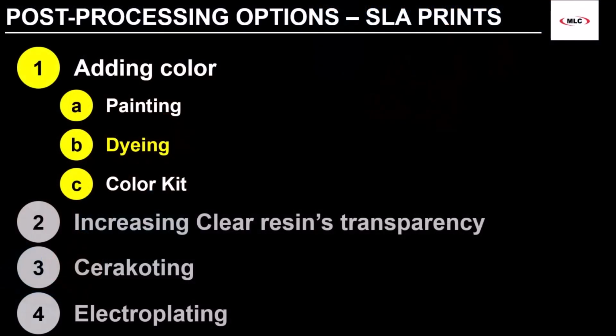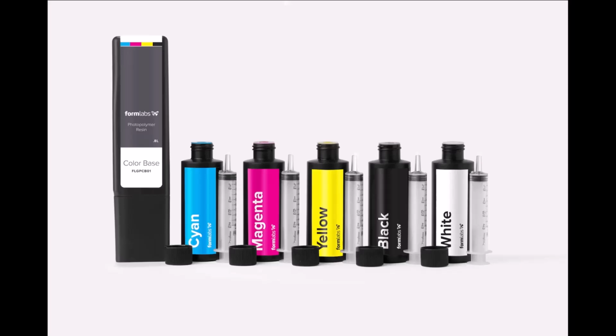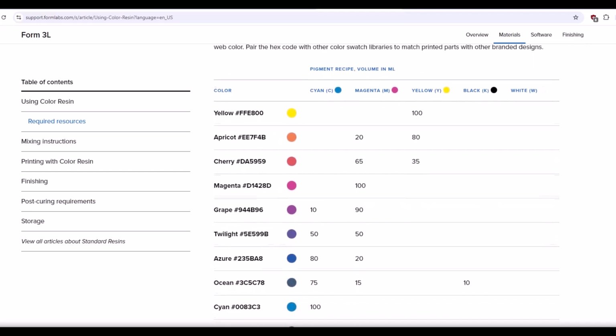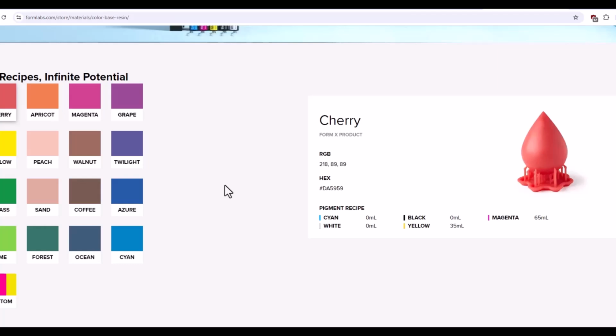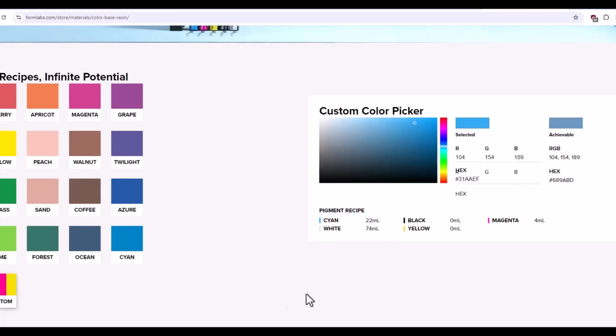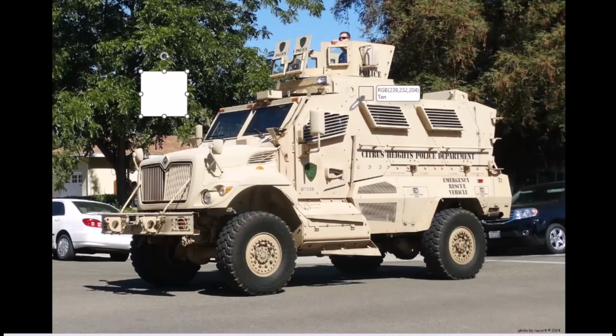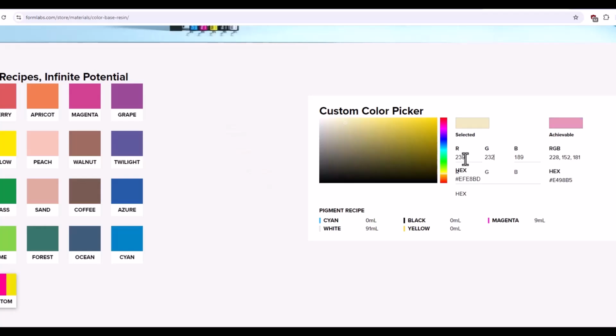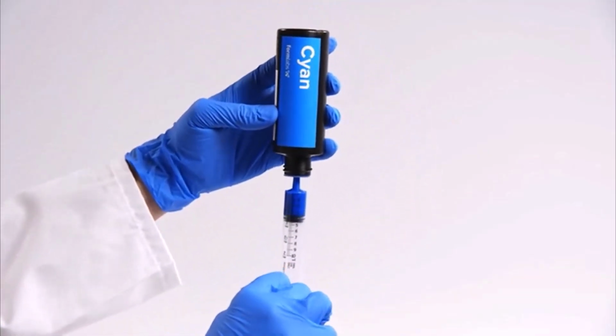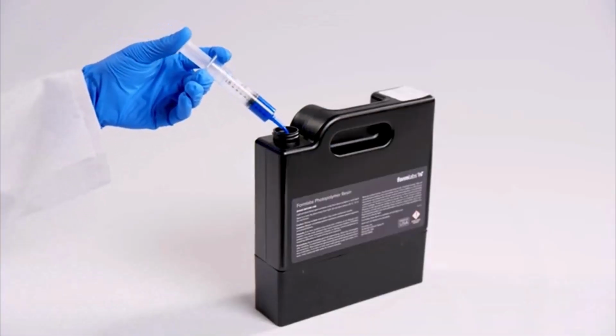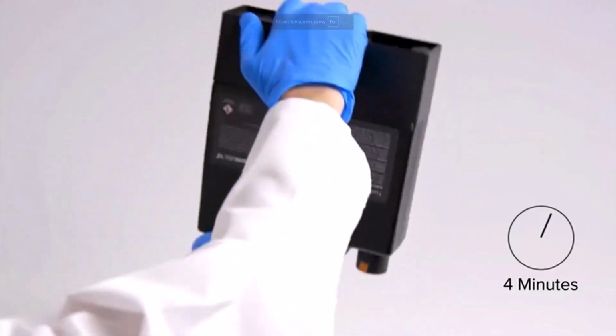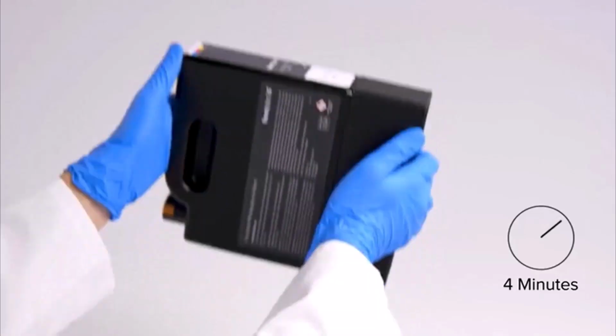The last common way to add color is to simply print with Formlabs Color Kit. The color kit consists of an 800 milliliter color-based resin cartridge and 5 pigments: cyan, magenta, yellow, black, and white, with their corresponding 10 ml syringes. Choose your desired color and follow the pigment ratio listed in the accompanying recipe book. You can also refer to the custom color picker in the Formlabs store profile for color resin to choose a highly specific color. Note that each recipe requires 100 milliliters of pigment. Extract these, inject these into the color base, close the cap, and shake for about 4 minutes. From here, the printing process and all the rest proceeds normally.